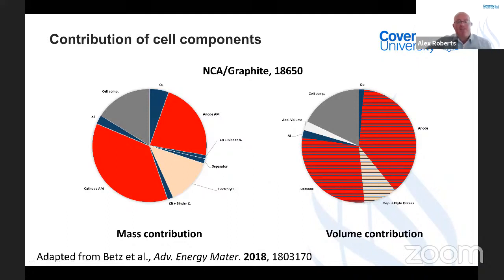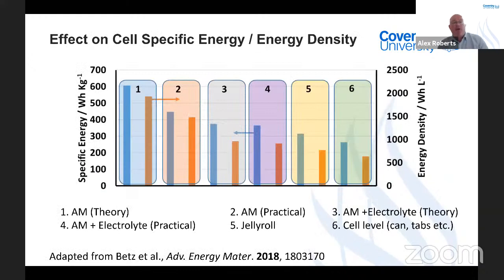So if we look at how this affects the results that we thought we had the first time, you can break this down. And they've done this in this work very nicely by looking at the gravimetric and volumetric energy densities here. So in case number one, you've got your active materials' theoretical capacities that you get purely from calculation. When you then consider the practicalities of, for example, maybe derating some of the electrodes to give a longer cycle life, you can see we have a drop in capacities. A drop in the energy densities.